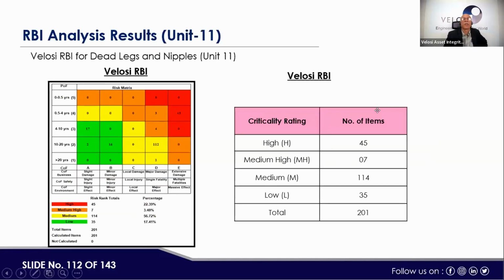Here, high risk equipment is identified as 107. Here, color wise, you can also see high, medium, low. Like this color, red, then maroon, then blue, yellow, and green. So high 107, medium high 95, medium 629, low 89, total 920. This is for unit number 11, 12, and 13. This is unit 11 alone, the same distribution. Like high 45, medium high 07, medium 114, low 35, total 201.